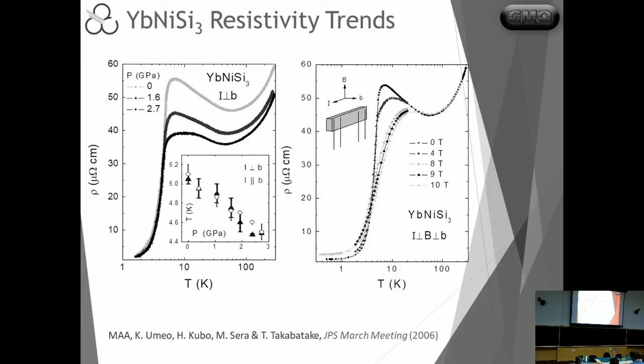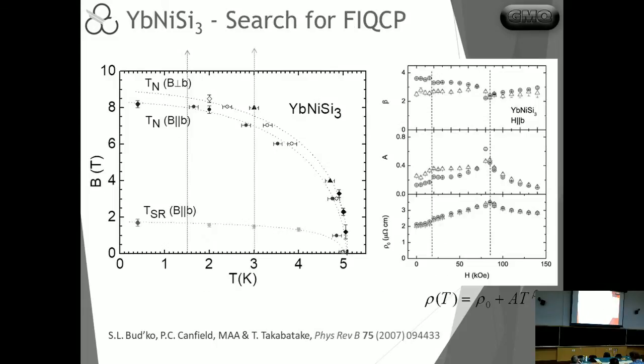So then we started working on some things that we could do at the time, right? So we could apply a little bit of pressure. We didn't have all that much. And then we could see that we basically destroy the Kondo maximum as we apply pressure, and we also destroy it as we apply magnetic field, which seems then that this could be a tunable system to start searching for quantum critical points. In the particular case of the ytterbium silicide, the best thing to do would be to look for the magnetic one, so a field-induced quantum critical point.